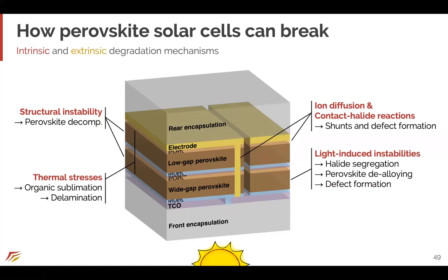Right, so these are all possible under light, which is a problem if you have a solar cell. And certainly there's extrinsic mechanisms like moisture and oxygen ingress, which can lead to decomposition as well. So for the intrinsic things, you basically just want to tune your perovskite compositions carefully. You want to choose your contact layers carefully and design internal barrier layers in many cases to try to block that ion motion, which is unique to the perovskites. In terms of the extrinsic mechanisms, probably the simplest design strategy is just to choose good packaging solutions. Certainly the better we can do in terms of intrinsically stable perovskites, the better off we are from an extrinsic perspective as well.